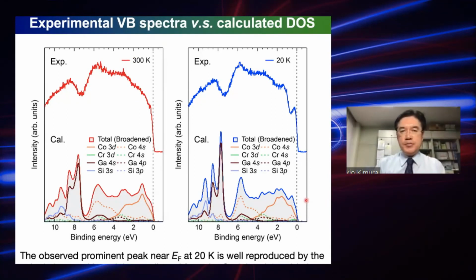Now I would like to compare the experimental valence band spectrum with the theoretical density of states, which was corrected by considering the cross-section of each orbital contributing to the DOS. We see good correspondence of the appearance of the peak in the experimental spectrum at low temperature with the calculated DOS, which shows a sharp peak here. Also, there is a dip in the theoretical density of states, which is totally consistent with the experimental result. And we now know that this sharp peak near the Fermi energy is mainly contributed by cobalt 3d and 4s orbitals. The disappearance of the dip and peak is also reproduced in the calculation for the tetragonal phase.